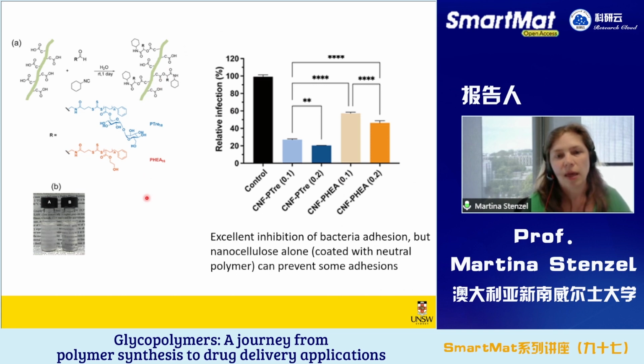And if we now incubate that with HUVEC cells, we found that we have a very significant reduction of adhesion. This is the amount of healthy cells infected by bacteria. If we add nanocellulose coated with trehalose, then we can lower this infection by almost 80 to 90%.